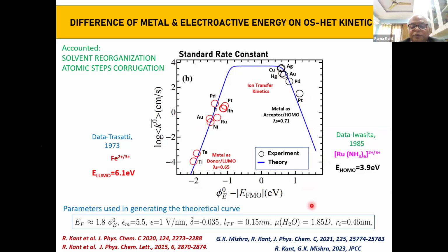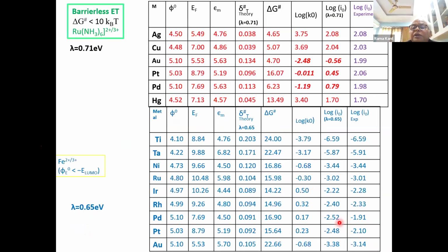The metal will have a specific work function and Fermi energy. That is circumvented by using this kind of approximation, by averaging over various ratios of work function over Fermi energy, which is about a 1.8 factor for good metals. And there are calculated numbers and how it matches, except this gold, where the deviation is large and doesn't satisfy. Others satisfy the theory much more coherently.